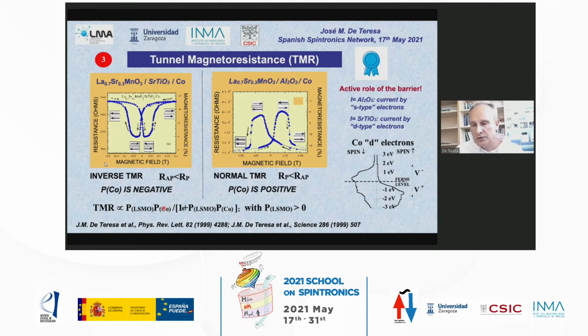How was this possible? This was possible if the d electrons, the electrons from the d band of cobalt, were carrying out the tunneling and not the s electrons, because the s electrons are positively spin polarized, as had been demonstrated in standard junctions with alumina barriers, such as in this one. But this insulating barrier here, this interface between cobalt and strontium titanate, was favoring the tunneling of d electrons, and the d electrons have more density of states for the spin down subband. This could explain this inverse tunneling magnetoresistance. So there was an active role played by the barrier. Okay, good.